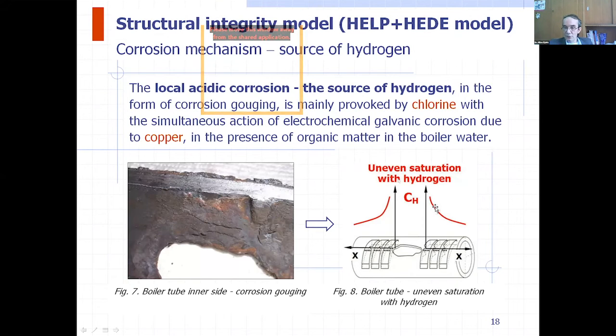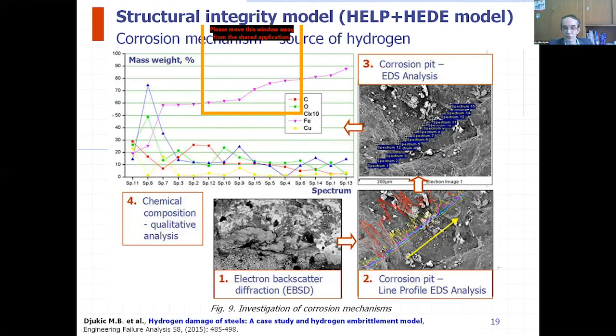Uneven saturation with hydrogen was due to the local acidic corrosion, which was the source of hydrogen, and provoked the corrosion gouging. As you can see here, that gouging was mainly provoked by chlorine with a simultaneous action of electrochemical galvanic corrosion due to the copper in the presence of organic matter in the boiler tube. Just briefly, we investigate the corrosion mechanism.